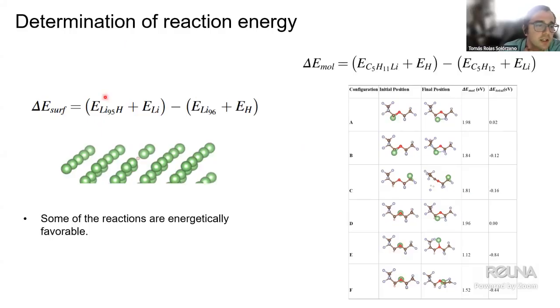On the other hand, we also calculate this change here. We calculate the energy of a surface, removing one of the lithiums and replacing it with a hydrogen, adding the energy of that isolated lithium atom that would have been removed, and subtracting the surface of the lithium plus the energy of the hydrogen atom. So what this gives us is a before and after for the surface and a before and after for the molecule. For the molecule, we take the hydrogen and replace it with the lithium, and for the surface, we take away one of the lithiums and replace it with a hydrogen.